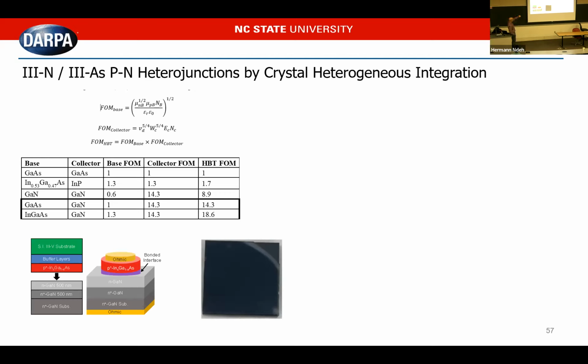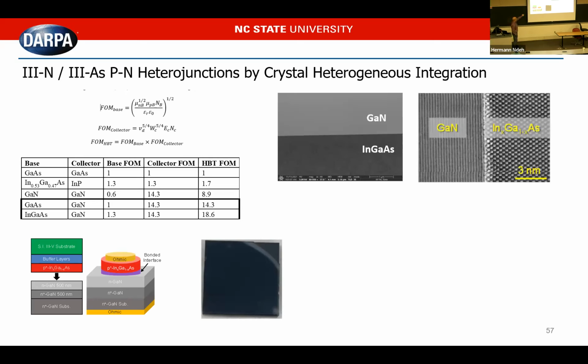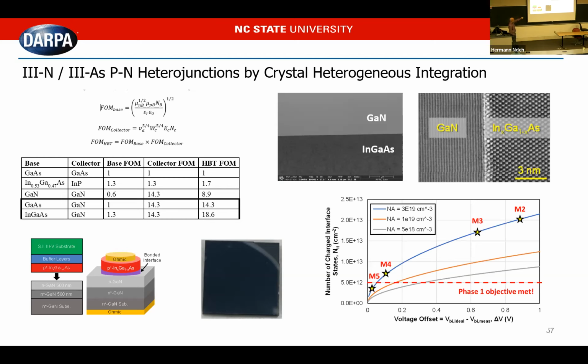This is a picture. This is just the edge of a wafer of a 1 centimeter by 1 centimeter device. Here's an SEM cross section with GaN bonded to InGaAs. And with this, we've obtained defect levels that we think are substantially lower than what people have attained doing similar work, and better PN junction results. So I think there's still a lot of work to be done to actually get to the point where we can make a good PN junction interface to make a good HBT. But I think we have the best capability to do that here.